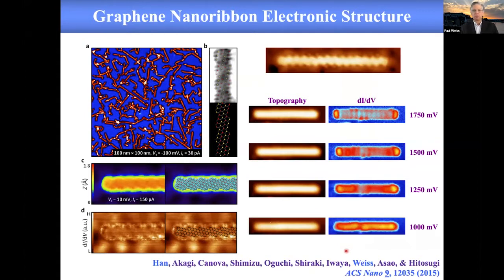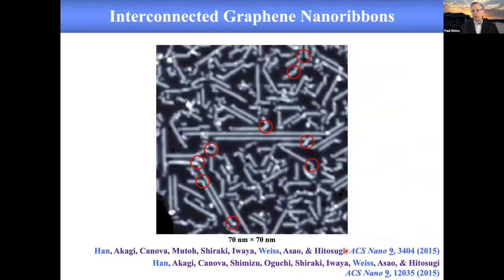There was a comment written on this paper which said, under different reaction conditions, we get a different product, so your mechanism must be wrong. And we kind of said, okay, but at the same time, we wanted to take the comment seriously, so we reproduced those authors' conditions and showed that we did indeed get a different product, although we believe the mechanism was still correct. But what we noticed when we did that was, instead of getting the straight chiral graphene nanoribbons, we got these junctions. And junctions, to me, look like contacts. And so we said, well, here we have these contacts that we were trying to figure out how to make. Let's explore them spectroscopically. And so we did that.